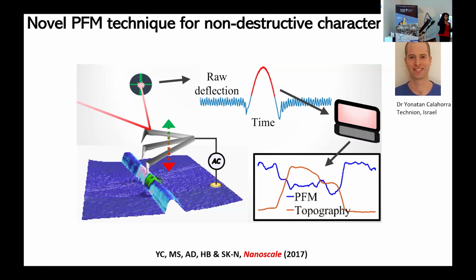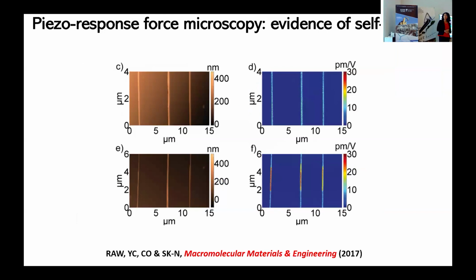But in this case, rather than scanning the tip continuously in contact mode, we use an intermittent contact method by which we can apply a very high frequency AC field just at the point of contact, and then we can deconvolute the response to work out what the piezoelectric response is. So this is a very powerful technique, and it opened up the door for us to be able to study these materials better.